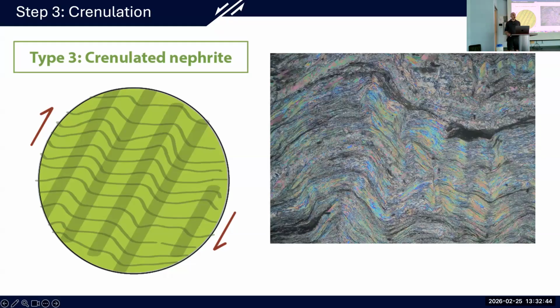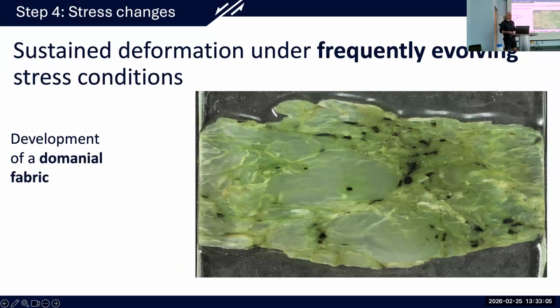But again, this is a complex system where stresses at a local scale are subject to constant reorganization. And it's in fact this constant reorganization that we need in order to create this kind of chaotic fabric throughout the rock. And so this brings us to our final condition, which is that deformation needs to frequently evolve in the stress field orientations.